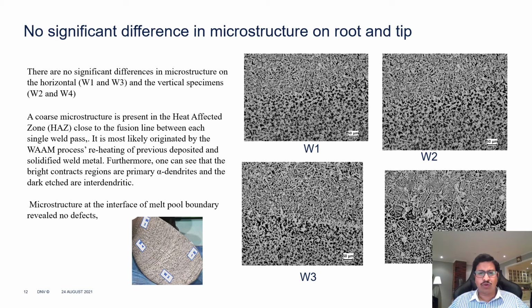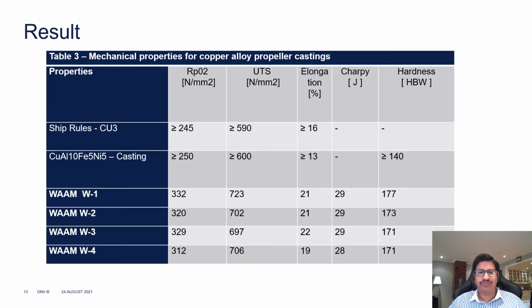And this micrograph was similar to the earlier scientific literature by some academics on wire arc additive manufacturing, especially on nickel alloy. And the results, when we compared with normal castings, where we require a yield strength of 250, we achieved almost 330 megapascals or Newton per millimeter square, around 320, and tensile strength was approximately 700, 690. Elongation was almost within the range.